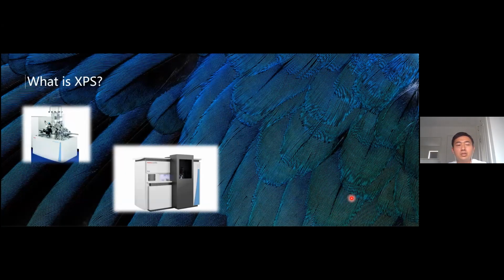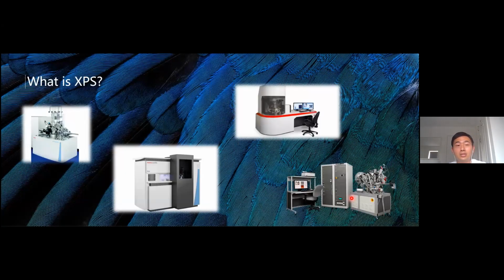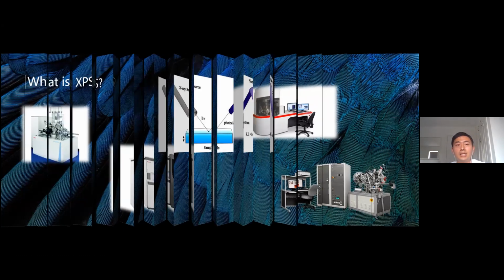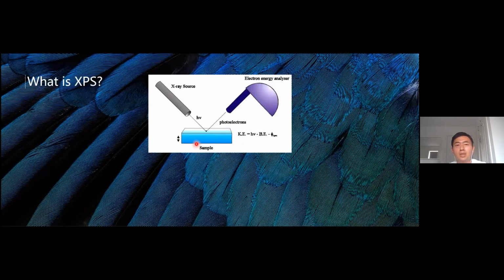XPS instruments may look different, but the principle is the same. When the X-ray source irradiates a sample, it can penetrate microns deep into the sample, but only the top 10 nanometers' worth of photoelectrons are able to escape from the surface without losing energy. These electrons will be collected by the analyzer.